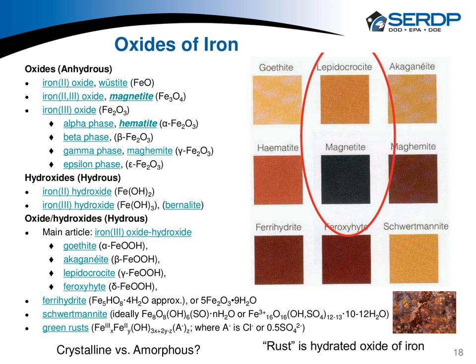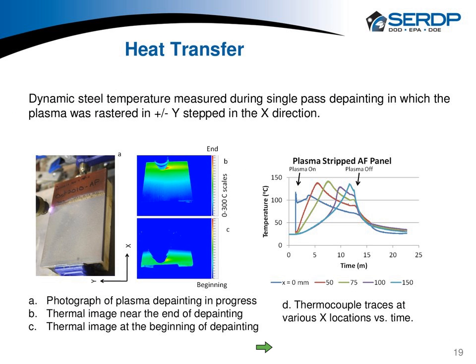Well, that iron is going to want to reoxidize, especially in an atmospheric environment, in a Navy yard with salts, etc. And very commonly, water is involved. I don't have the equations here for the formation of rust, but in the presence of water, iron will form various different oxides, especially hydrous types of oxides that are fairly porous, that are weakly bound, that are not desirable for painting. Now, in the case of plasma, I'm going to come back to this and show more data, but we have found that the oxides formed with plasma, because the plasma is in itself an oxidizing environment, tend to be very stable forms of iron oxide, magnetite or hematite, iron +2, iron +3, up to the full oxidation state. So one can easily see that we're in between these two types of oxides in terms of color.